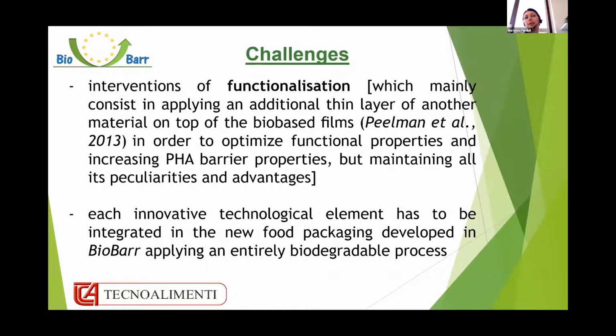The point is that, as already mentioned by Maria before, PHA as it is has some weak points for applications as flexible films for food packaging, in particular related to the low barrier properties. So we decided that the best solution was to functionalize this material, applying an additional thin layer of another material on top of the bio-based films in order to optimize the functional properties and improve this weak point, but maintaining all its peculiarities and advantages in terms of biodegradability in particular.